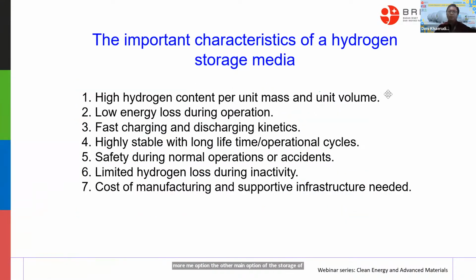So what are the important characteristics for the hydrogen storage media or sorbent material? If I conclude, there are 7 points here. Number 1, high hydrogen content per unit mass and unit volume, which we need to be concerned about. Number 2, low energy loss during operation. We also need to pay attention to this, because hydrogen is a very small molecule. Number 3, fast charging and discharging kinetics, regarding when we store and when we want to release or use it. Number 4, high stability with a long operational lifetime. For sure, every equipment and technology, we want a long operational life cycle.